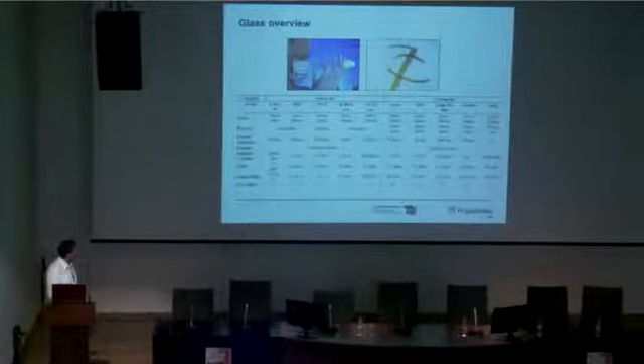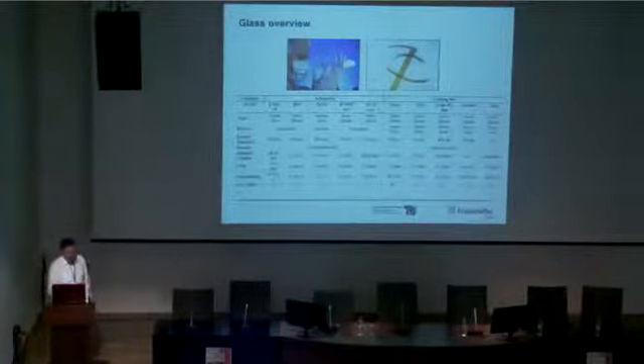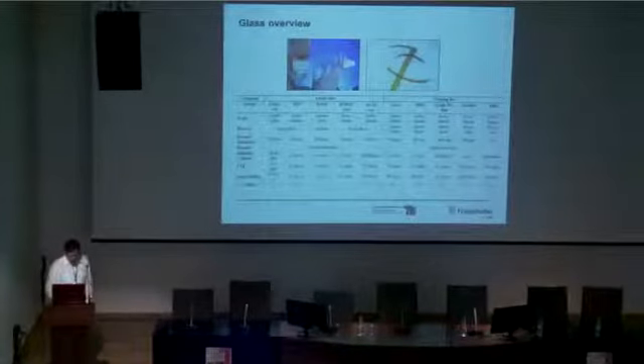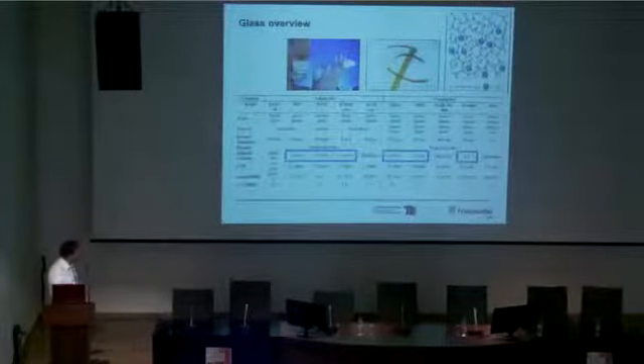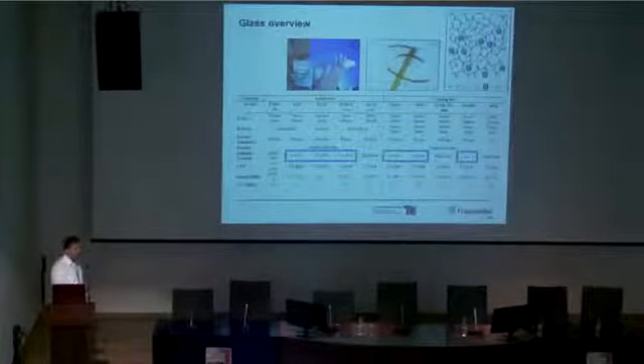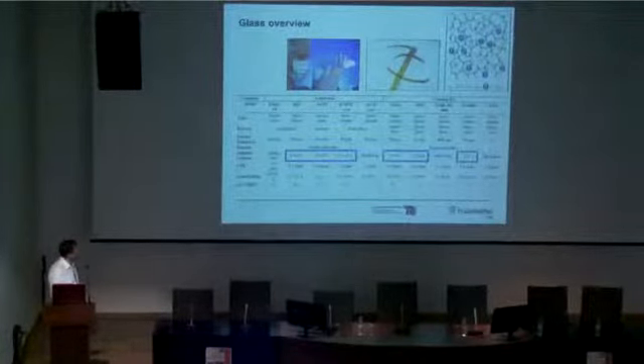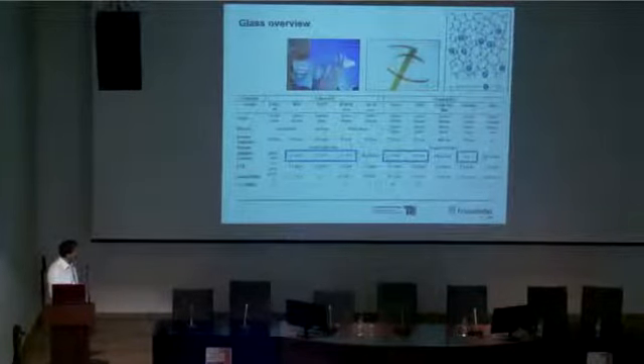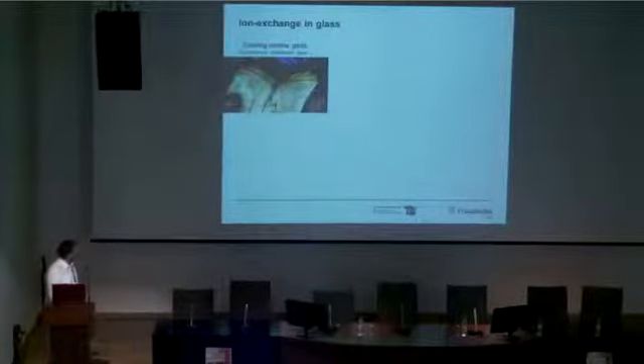The next point is that we have to select a glass that contains alkali ions, because we use an ion exchange technique. This means we use glass that has sodium ions inside the glass matrix, and these sodium ions have very weak bonds, so they are exchangeable with other alkali or other monovalent ions, and then we can increase the refractive index of these glasses. So we use ion exchange technology, and this is not a new technology.